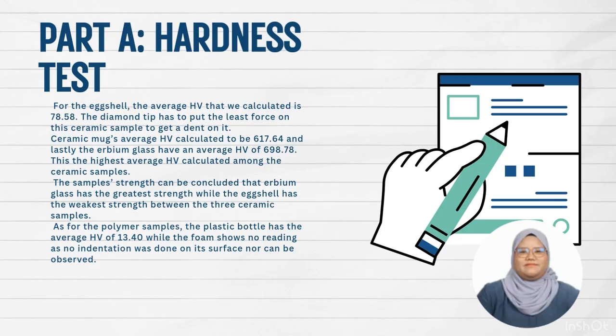Part A, the hardness test. First, we will go through the ceramic samples. Firstly, the eggshell. We have calculated the HV of 78.58. Next, the average HV for ceramic mug is 617.64, and the erbium glass has average HV of 698.78. The highest average HV calculated is the erbium glass. For the polymer sample, the plastic bottle has the average HV of 13.40, while the foam shows no reading as no indentation was done on its surface nor can be observed.